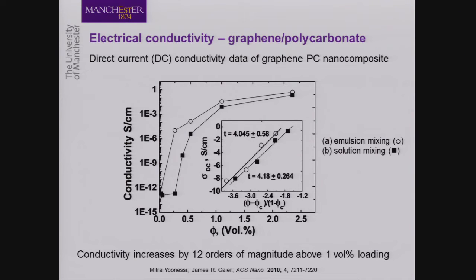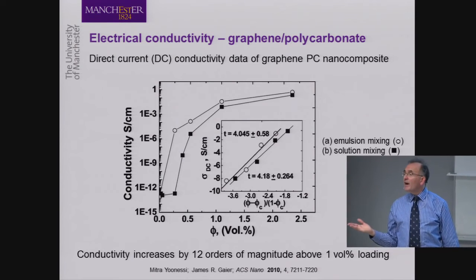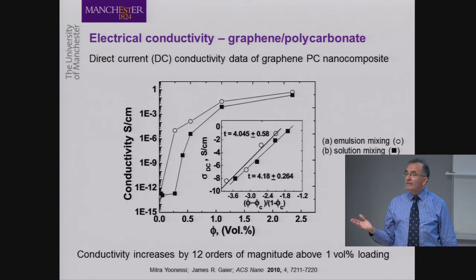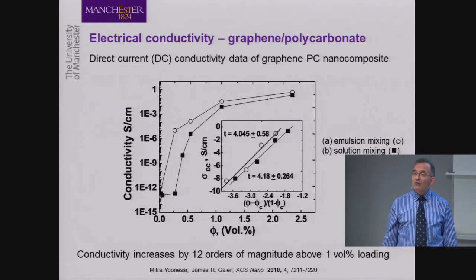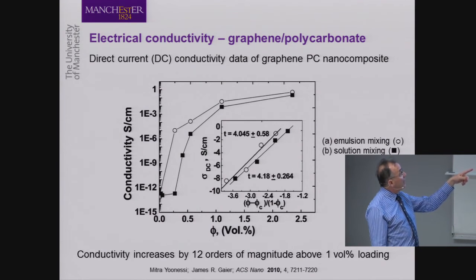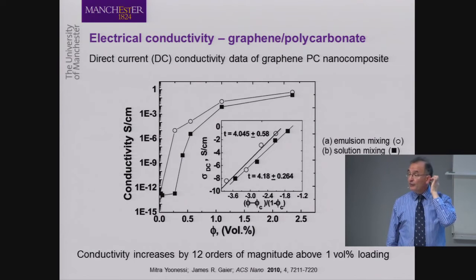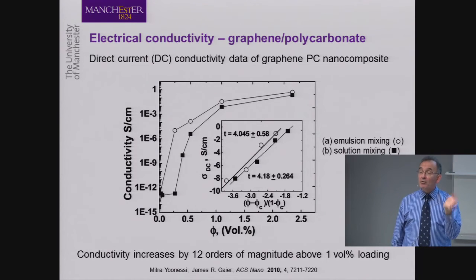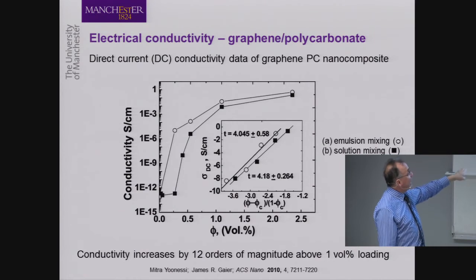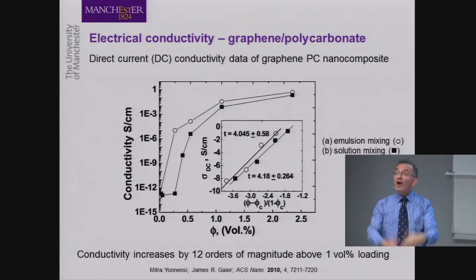The other significant property that we mentioned at the beginning of the talk is the electrical conductivity. And if we look at thermosets or thermoplastics, they are not electrically conductive. They resist electrical flow. But if we introduce 2% by volume graphene, then we can see that the electrical conductivity increases by 12 orders.